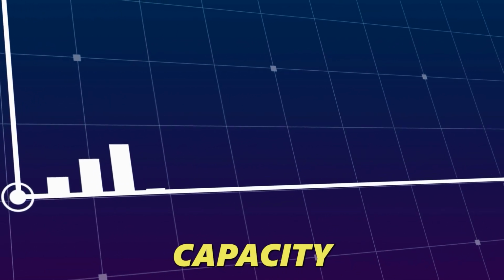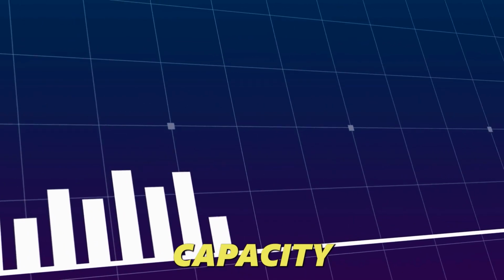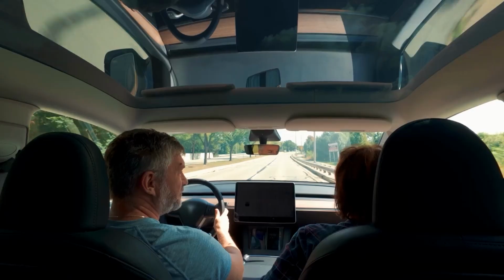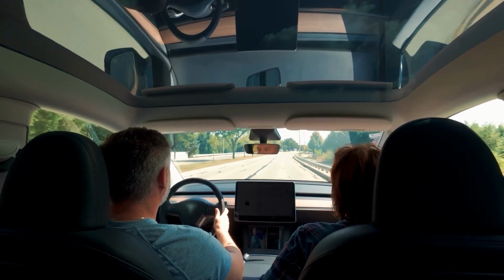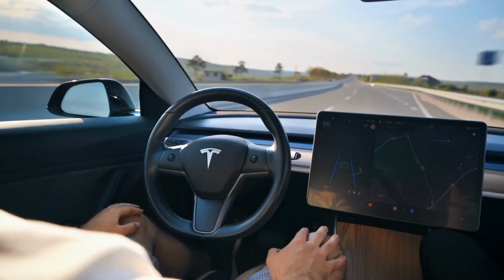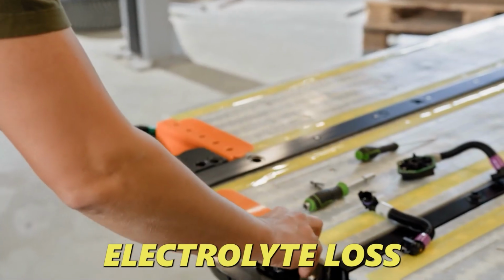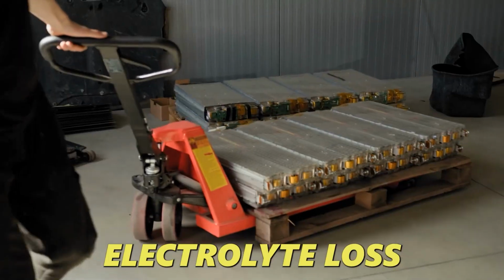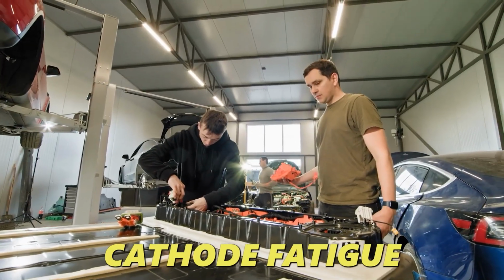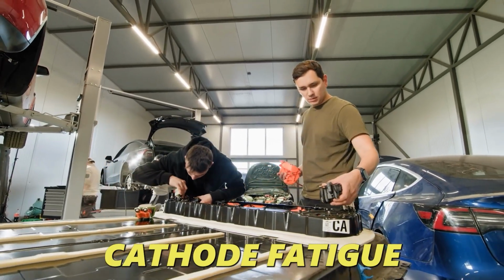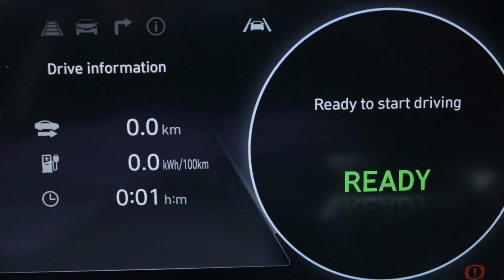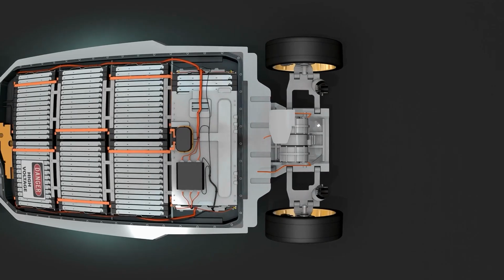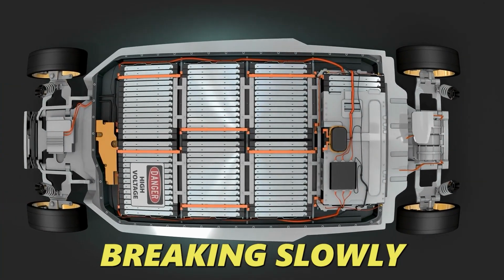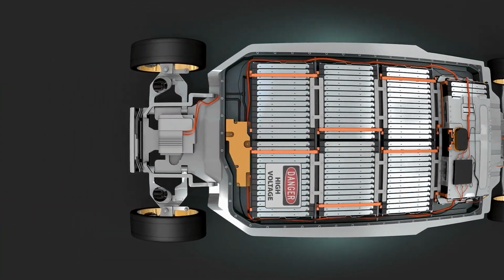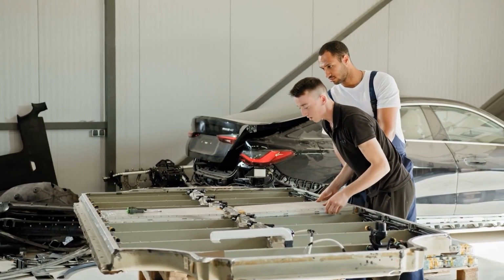If you've noticed your battery appearing to hold its capacity reasonably well for 2 or 3 years, then suddenly dropping, you've experienced this. It's not your imagination, and it's not a random defect. It's the cumulative effect of SEI growth, electrolyte loss, and cathode fatigue reaching a threshold where the discharge voltage can no longer support your vehicle's minimum power requirements. The battery hasn't suddenly broken. It's been breaking slowly, invisibly, for years. And one day the accounting comes due all at once.